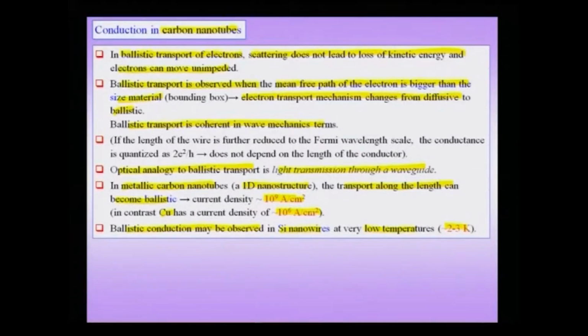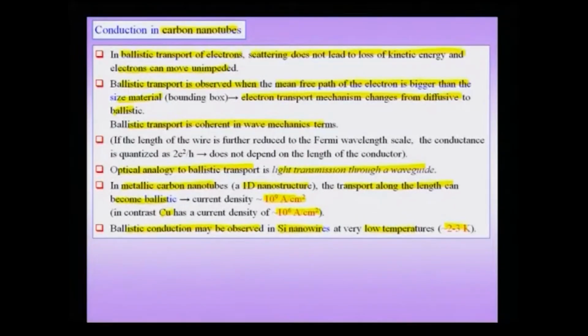And there are other systems like silicon nanowires too, wherein we would expect some kind of ballistic transport at very low temperatures. Of course, we have to note that this metallic carbon nanotube has to be defect free, because if there are any defects in the nanotube, that would lead to scattering, which will not give us this kind of high current density. So, it is indeed surprising that in nanotubes you can get very high conductivities and very high current densities, which is coming from the fact that the length scale of the problem has gone to nano size.